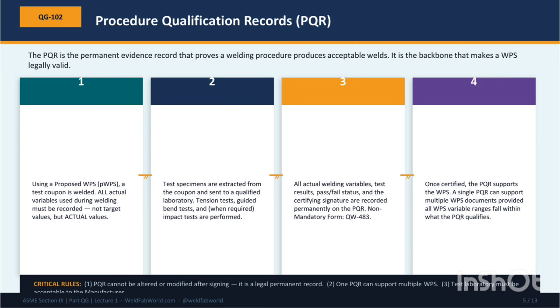Step 1. Weld a test coupon. You start with a proposed WPS. We call it a PWPS, lowercase p, and you use it to weld a test coupon. The critical point here is that you must record the actual values used during welding, not the target values, not the range from the WPS, but what actually happened in the test. If the target current was 120 amps but the actual average was 118 amps, you record 118.